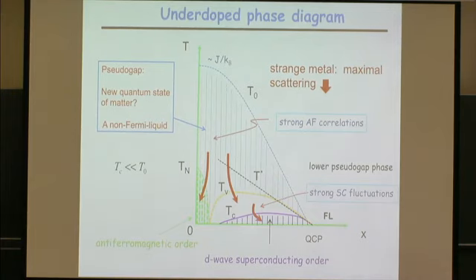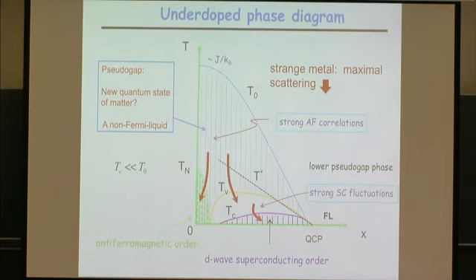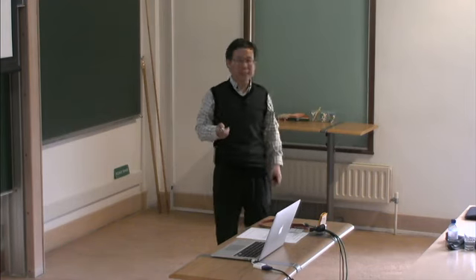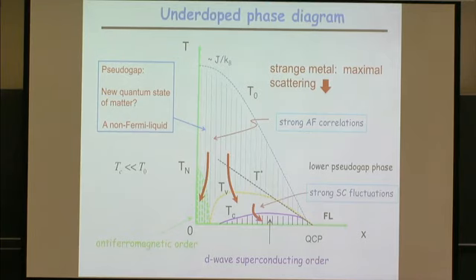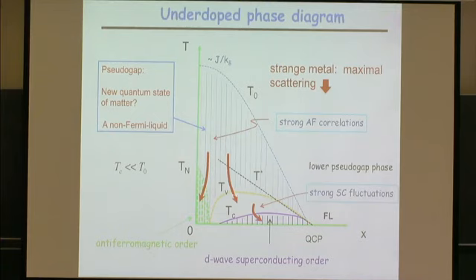And there are actually many condensed matter systems where you have long-range antiferromagnetic ordering and a superconducting state in the phase diagram. But there's a very important distinction: in systems like iron pnictides, heavy fermion systems, and organic systems, it looks like the normal state is not that different from a Fermi liquid. So basically, it's an order competition between two different symmetry breaking states. But here, it looks like there's a wide region of strongly correlated fluctuating state, which behaves like a non-Fermi liquid.